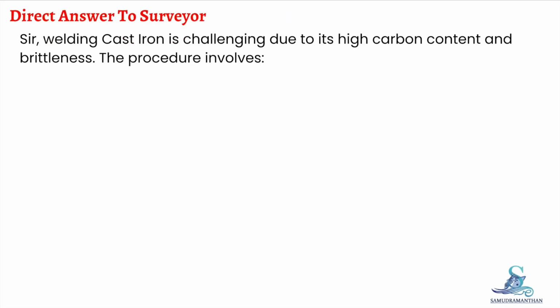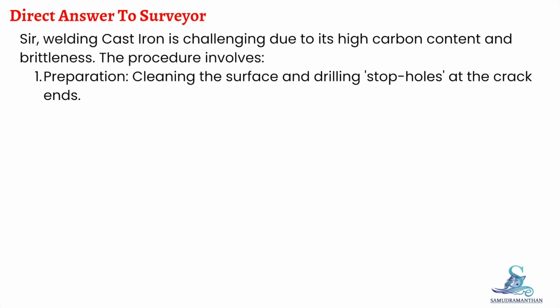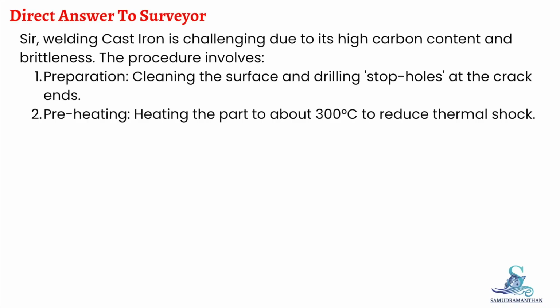Direct answer to surveyor. Sir, welding cast iron is challenging due to its high carbon content and brittleness. The procedure involves preparation, cleaning the surface and drilling stop holes at the crack ends. Preheating, heating the part to about 300 degrees C to reduce thermal shock.